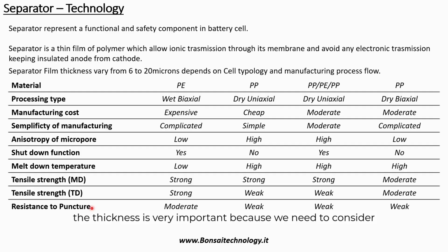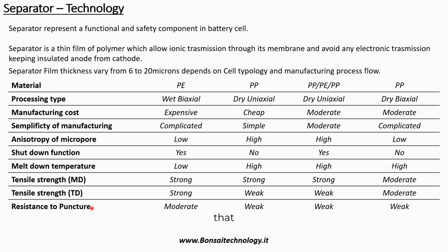As mentioned before, the thickness is very important, because we need to consider that we can have some particles on the electrode surface, we can have some cutting burrs, some debris, some contaminants that during the working life of the cell can touch the separator. I mean, these contaminants are very, very hard particles, and can create a micro hole in the separator, and in this way this particle can put anode in communication with cathode and make some short circuit.